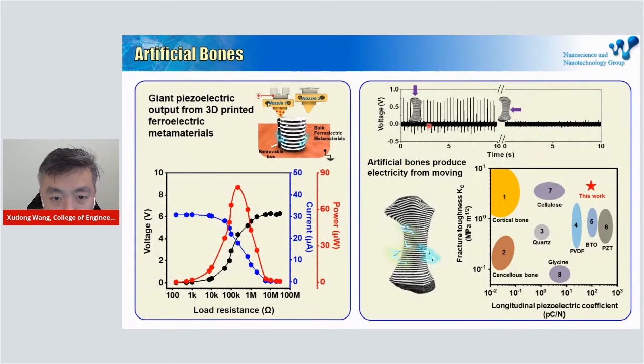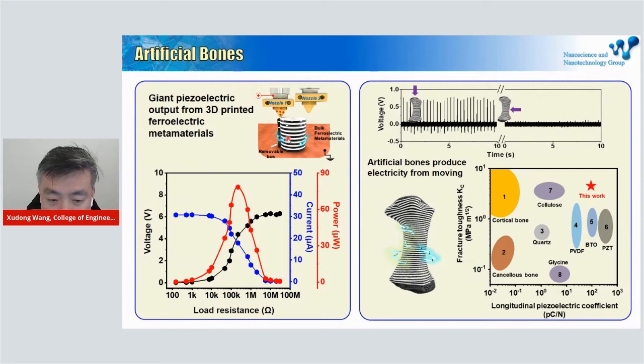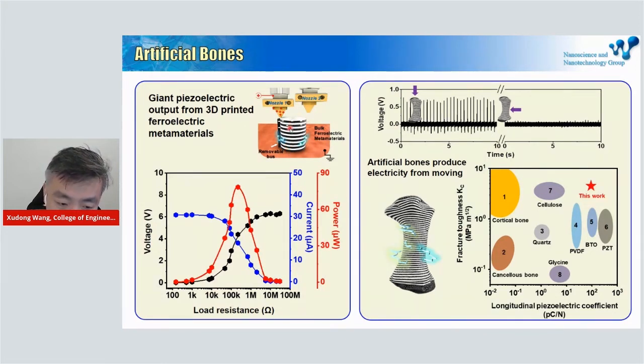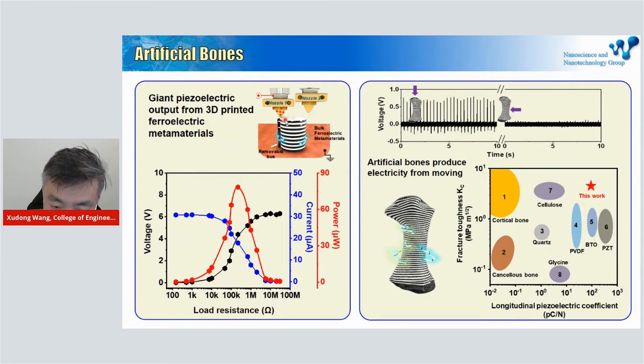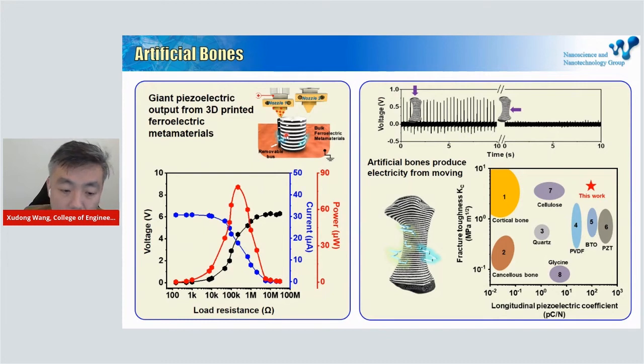In addition, based on the same technology, we recently created a multi-layer metamaterial structure that can be used as artificial bones. Bone itself is a piezoelectric material, meaning it can produce a very small amount of electricity based on the pressure it is subjected to, and it is also very tough and not easy to break. Typical ceramic materials are too brittle to be used as a bone structure. But our 3D printing technology combines soft ferroelectric material and hard conductive material printed together, significantly improving the toughness to the same level as real bones while retaining high electricity generation capability.